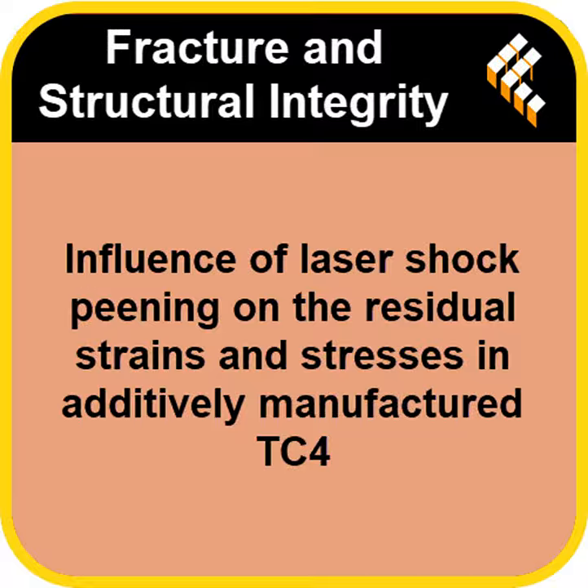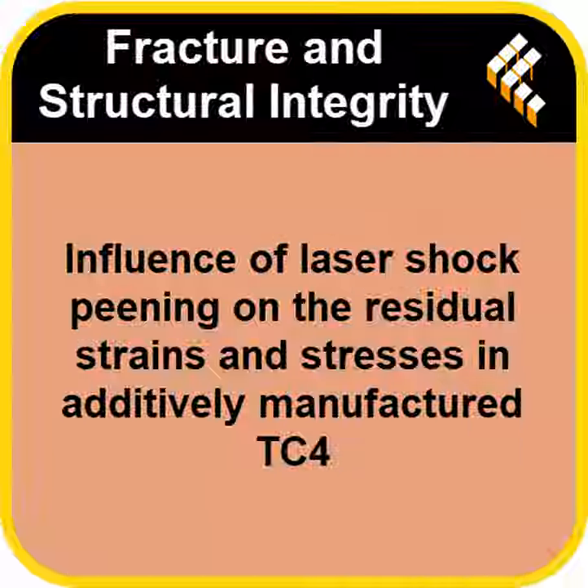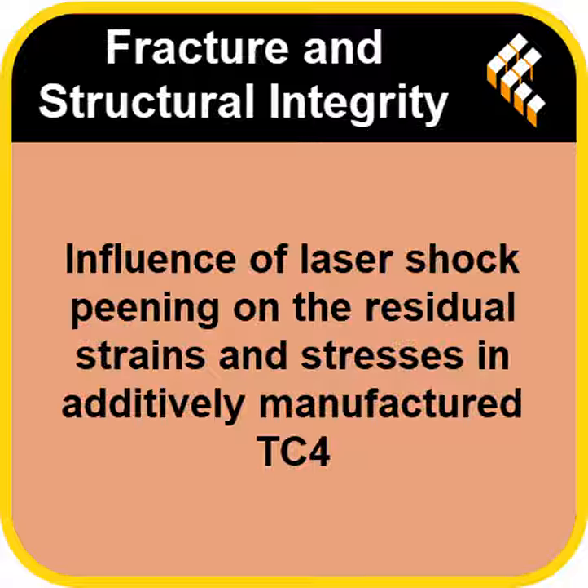So LS-DYNA does the physics simulation. Johnson-Cook tells it how TC4 specifically reacts to that physics. You got it. It defines how the material strength changes with strain, strain rate, and temperature, all critical under LSP conditions. And the big question, did the simulation match reality? Did the model accurately predict what they measured with the hole drilling? It did, remarkably well. The comparison showed the numerical model could reproduce the experimental results, both qualitatively getting the trends right and quantitatively getting the numbers right, with an error margin under 10%.